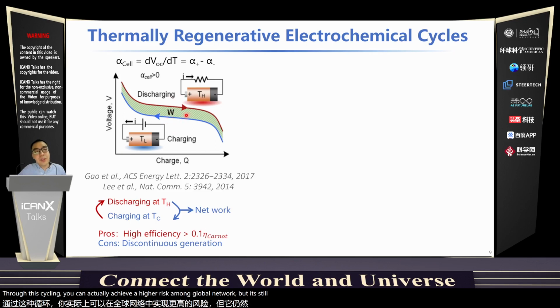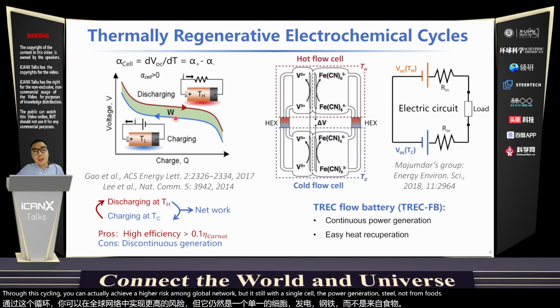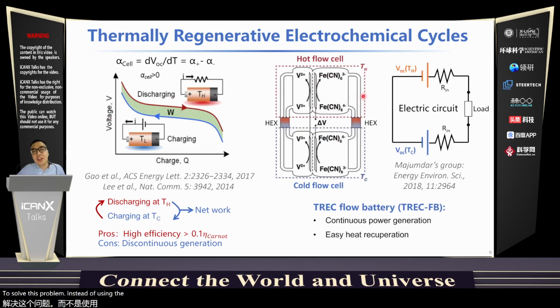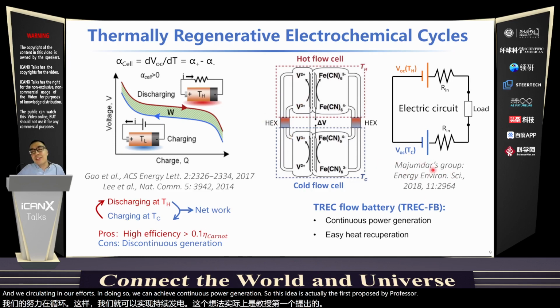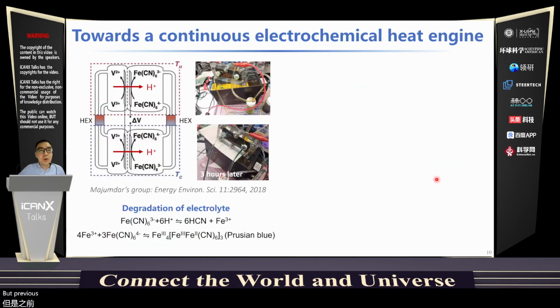But still, with a single cell, the power generation is not continuous. To solve this problem, instead of using a single cell, we can use two cells, two flow cells actually, one at high temperature, the other at low temperature. The redox reaction happens in the opposite direction, and we circulate the electrolytes. In doing so, we can achieve continuous power generation. This idea was first proposed by Professor Majumdar's group. But in previous work, the most challenging issue is the stable operation.